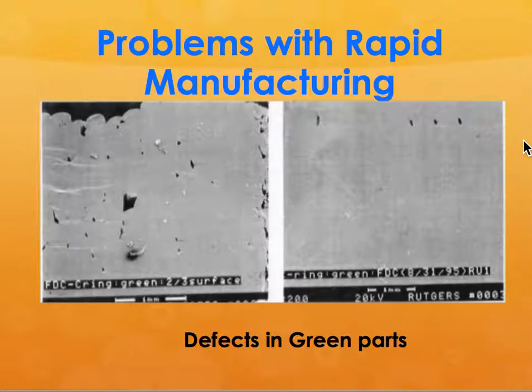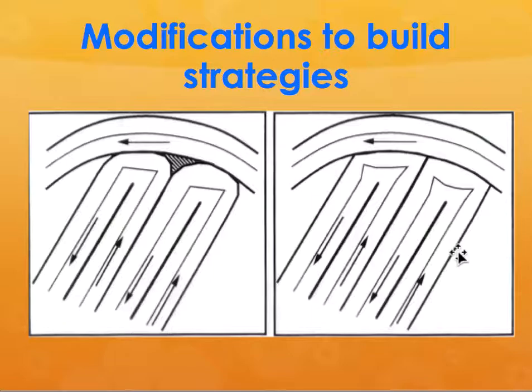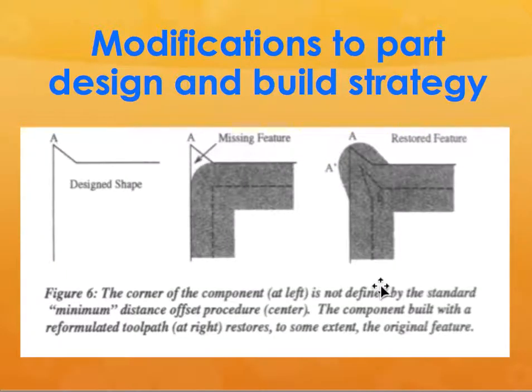In the case of metals or plastics, this may not be a big problem, but in the case of ceramics, these subsurface flaws especially are going to be starting points for failure. So you don't want that. What you have to do is build in modifications to the build strategies so that you do not have any gaps between these places. This happens mainly because you put in the outer perimeter and then fill the inside as a raster pattern. That's how most build patterns work. Between each set of roads, you will have a gap, so you have to avoid these gaps. Or you would build some excess and then machine off the excess area. Not the best way, but it can be done.